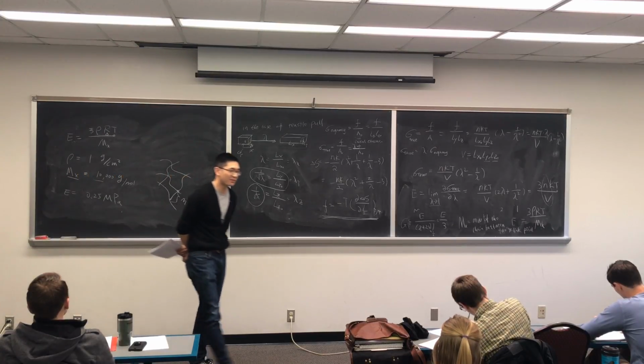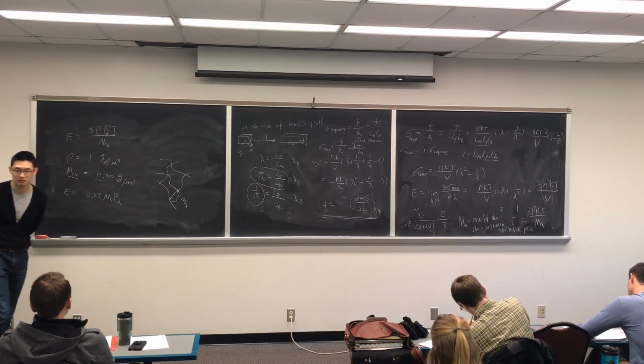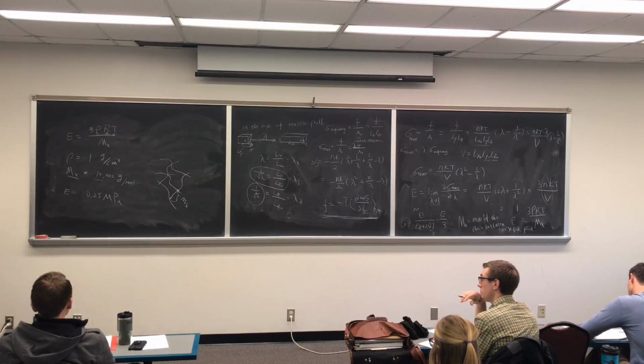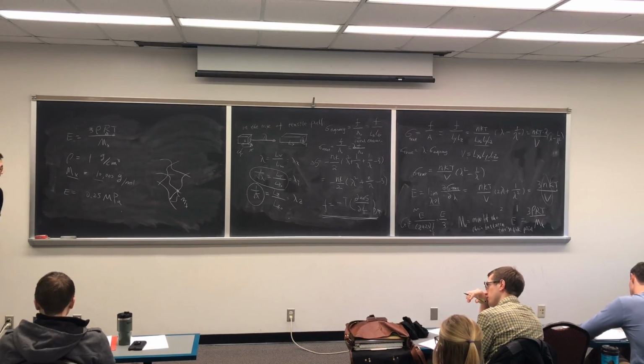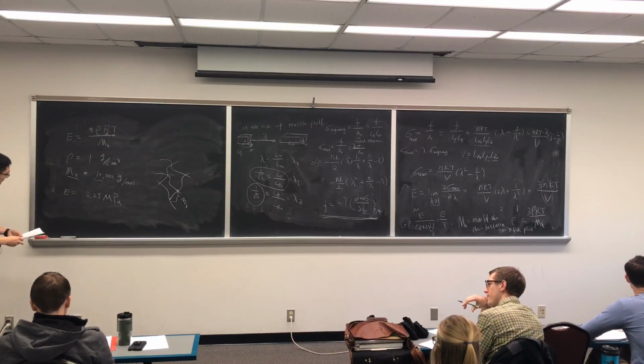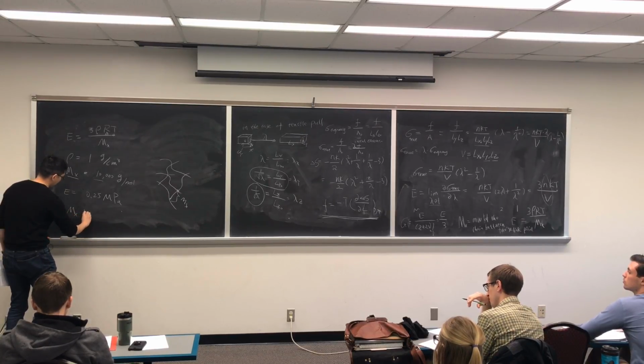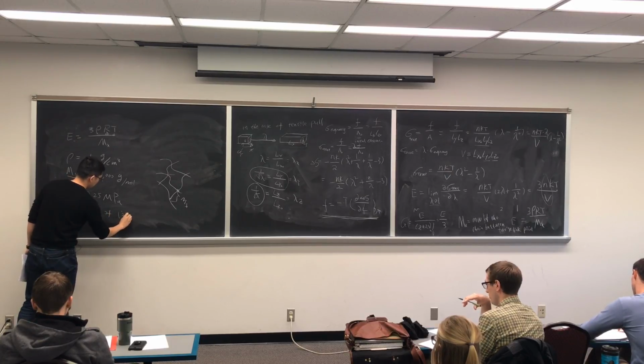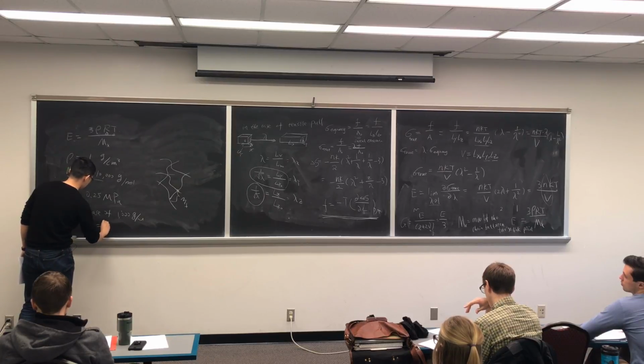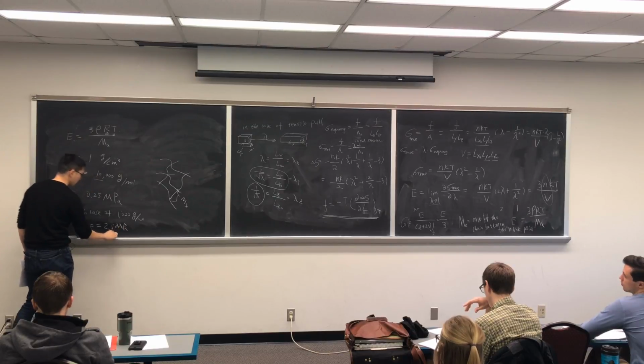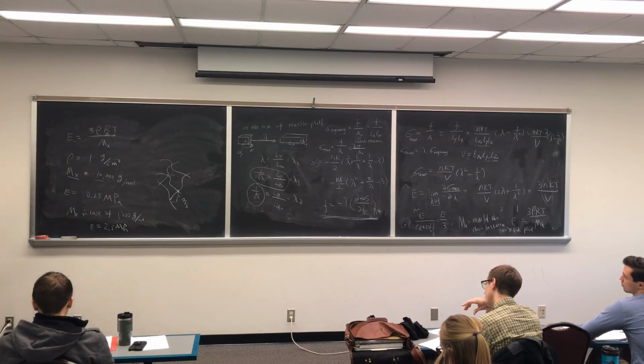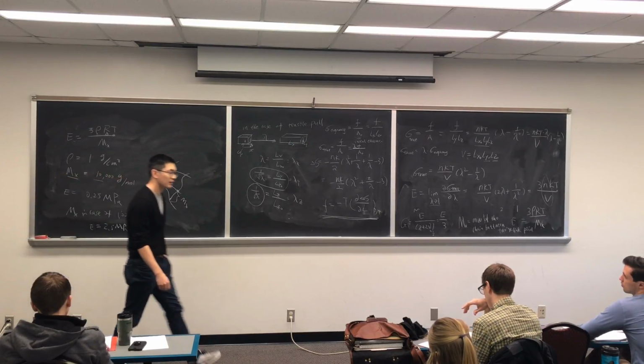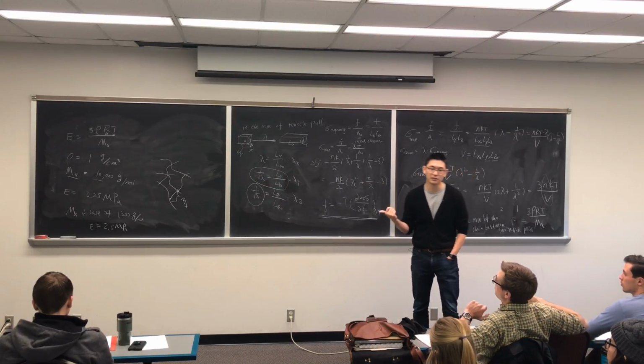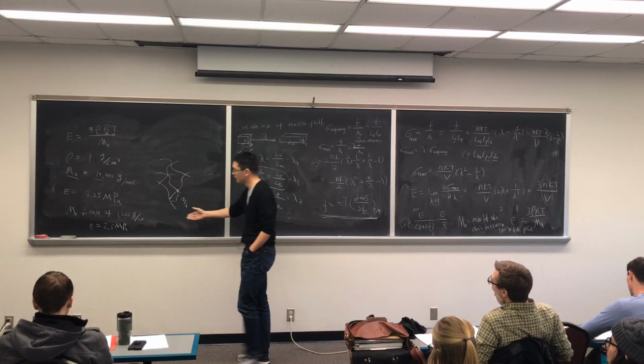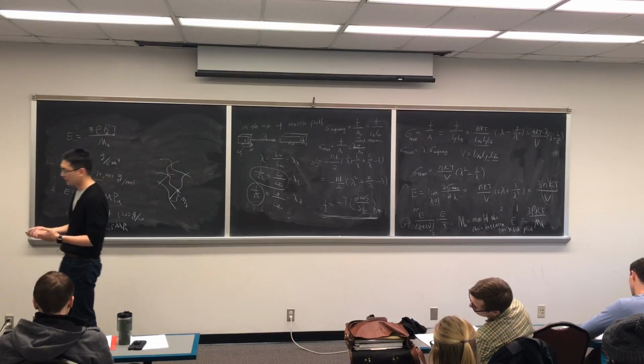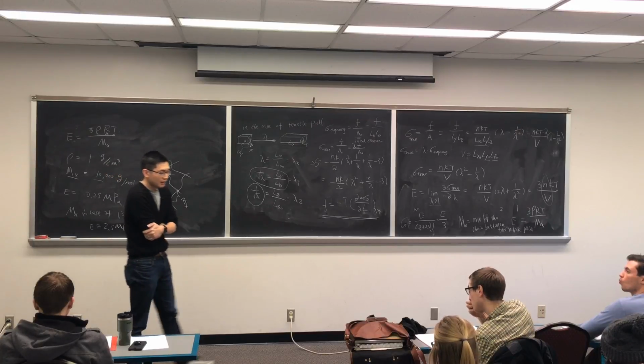That's pretty good in terms of theoretical descriptions for rubber material. It's on the same order of magnitude as rubbery material, okay? And if you have Mx 10 times smaller, the elastic modulus is about 2.5 megapascal. So this can also be measured for rubber band material. Okay, we can take a short break, then we can come back to discuss some of the limitations of this theory. We talked about many good parts of this theory, how you can use it to predict the mechanical property of rubber band. And we're going to spend another 15 minutes talking about limitations after a 5 minute break, okay?